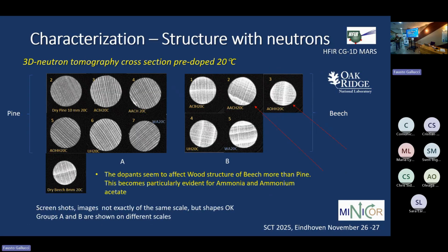Okay, so here what you can do, you take these radiographies, you do a lot of radiographies at different angles, and then you can calculate the 3D density, in particular of the hydrogen, which gives the strongest weight. So you can see that every dot here corresponds to the linear attenuation coefficient inside the material. So the brighter it is, the stronger the density of the hydrogen in principle. And you see that this is pine wood, which has quite a different structure inside the wood. And you see also that beechwood has a high density.